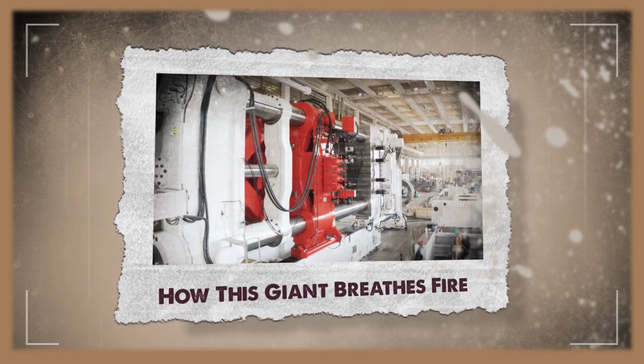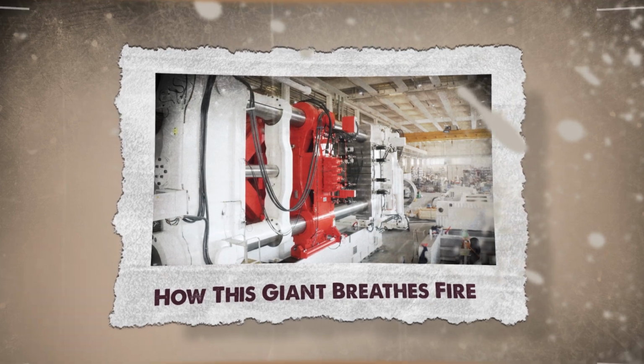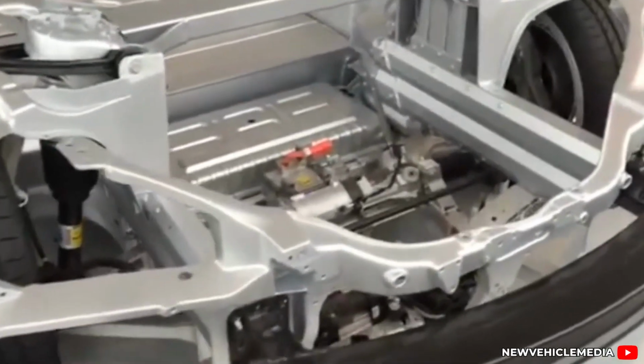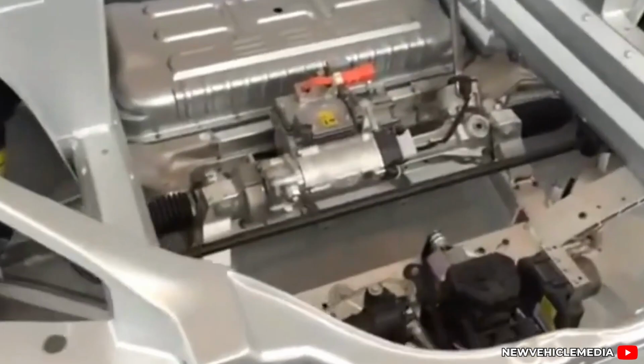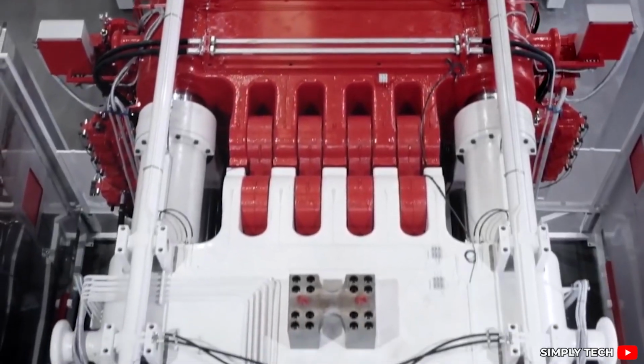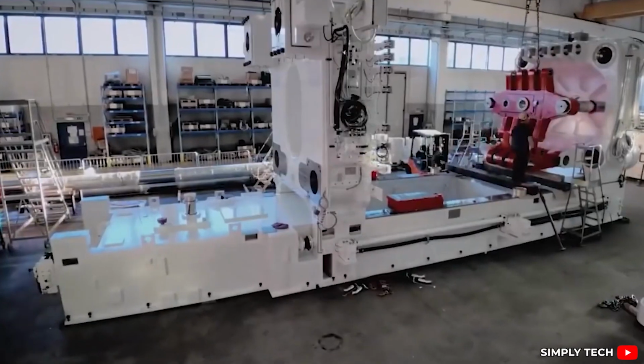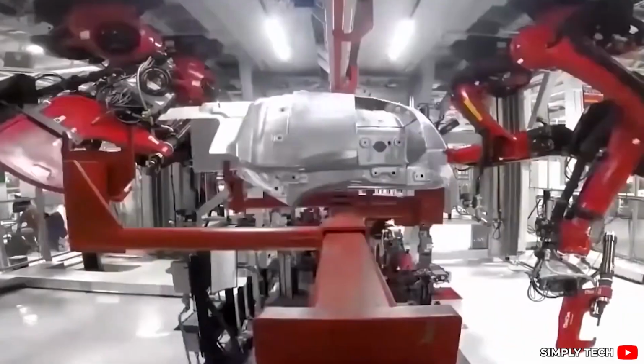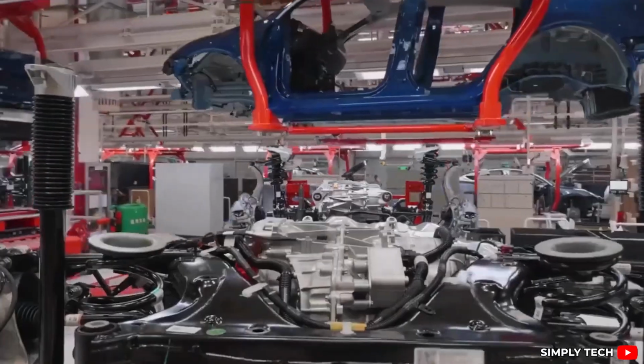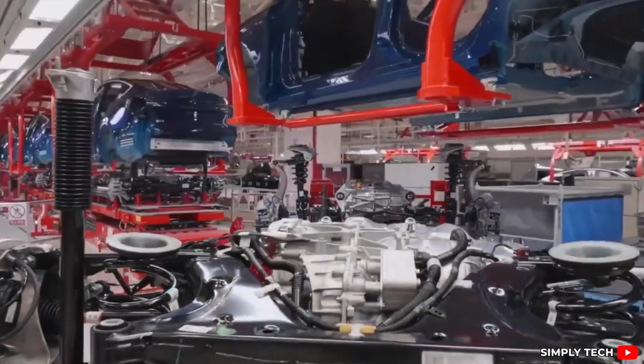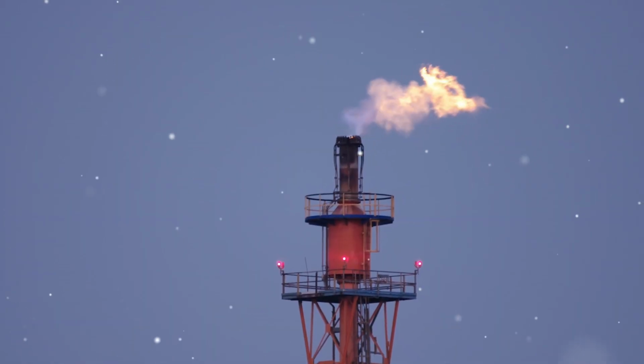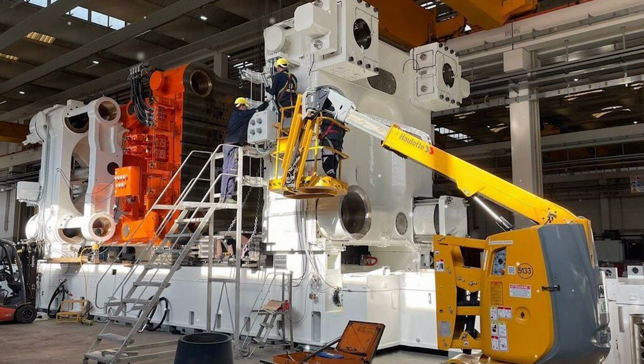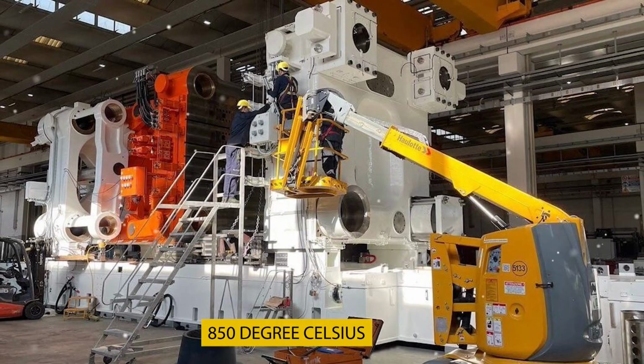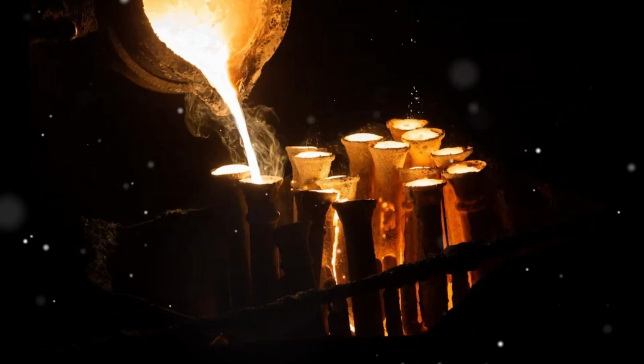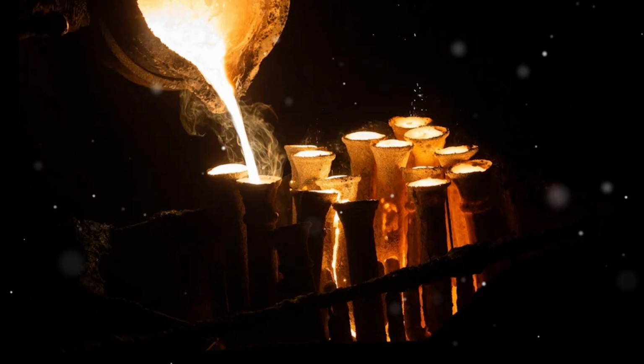How this giant breathes fire. Even though the scale has changed dramatically, the operating mechanism stays mostly familiar. The process begins with material preparation, where aluminum gets its moment of transformation. Tesla starts by melting down brand new aluminum ingots alongside leftover scraps from previous castings. These go into a furnace powered by natural gas, which is heated to a temperature of about 850 degrees Celsius, hot enough to turn solid metal into glowing, molten lava.